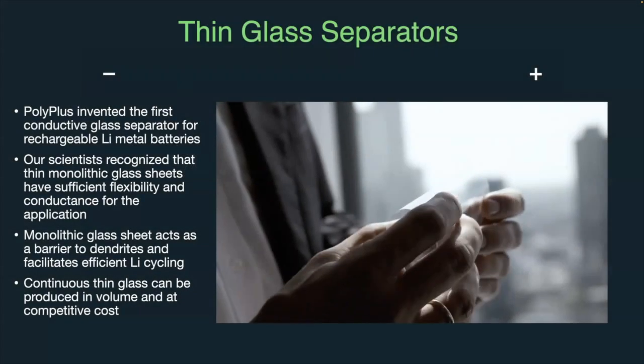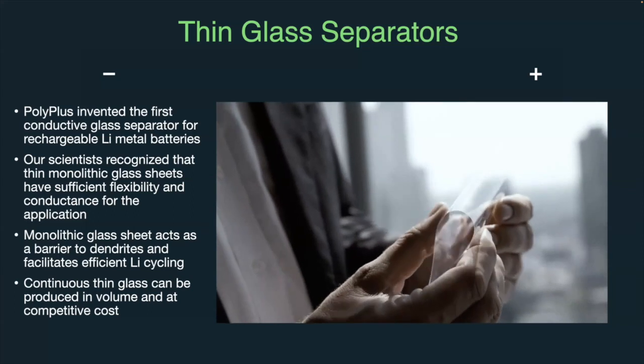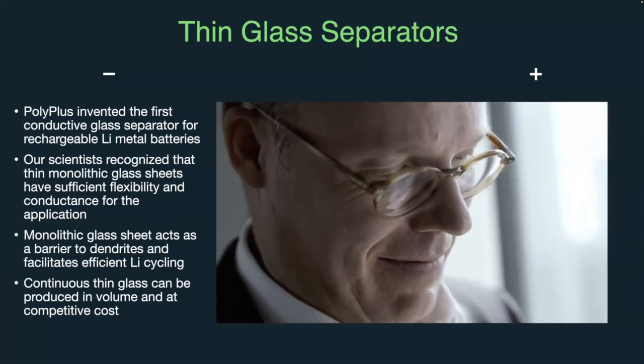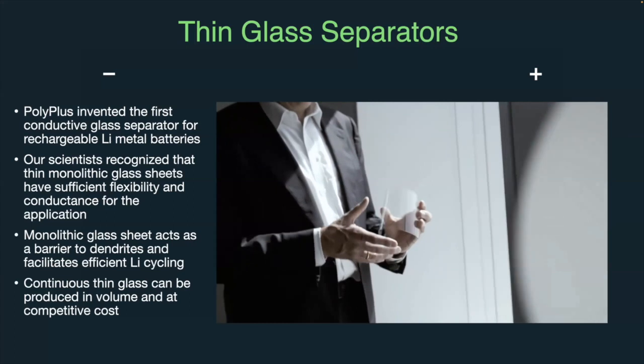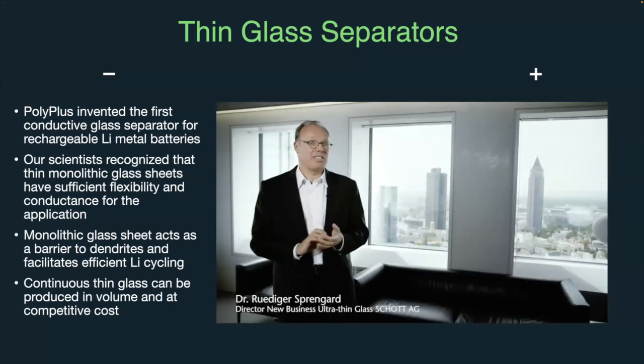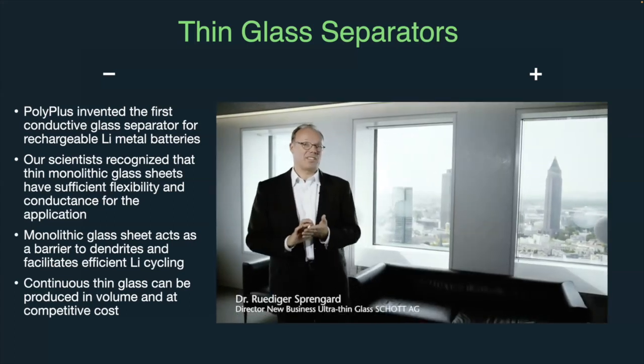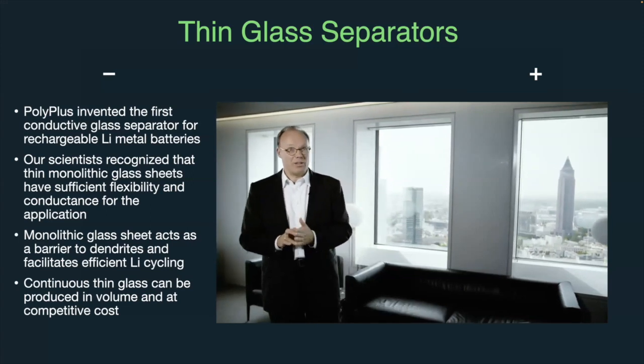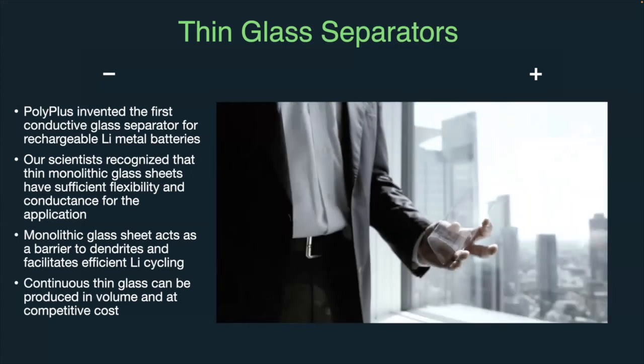Now, what you see there in the video is not a sulfide. That, again, is an oxide glass. But it just gives you a sense of how flexible glasses are when you get down to these dimensions of less than 100 microns thickness. These are roll-to-roll processes, which is what we're doing as well. So the idea then is the manufacturing process looks quite different.